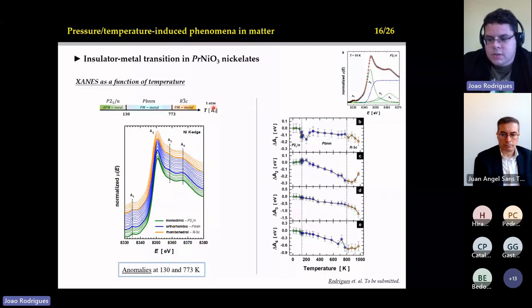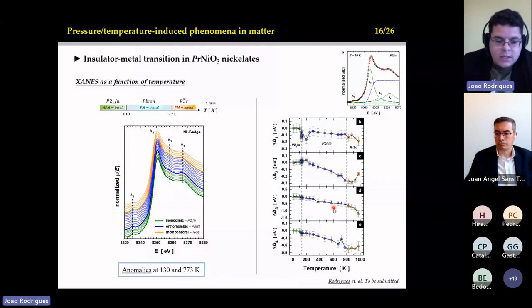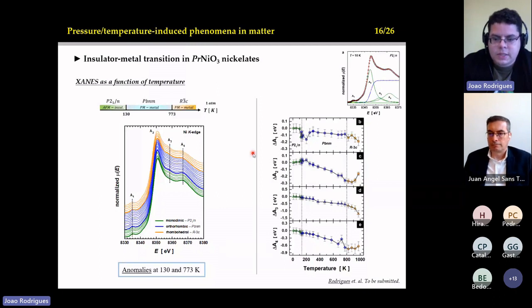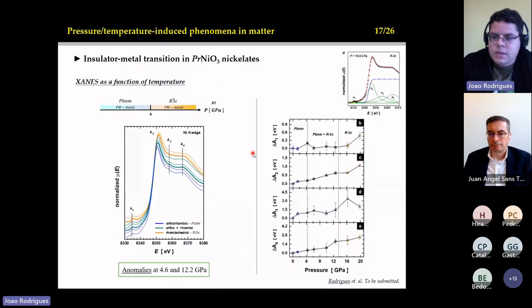And then we managed to see that we have the same effect occurring at the edge, the pre-edge signal A1, also occurring with the features of the XANES, which are called A2, A3 and A4. We have the same signal, and we can really understand what is happening with this material using both the XANES and the EXAFS parts.